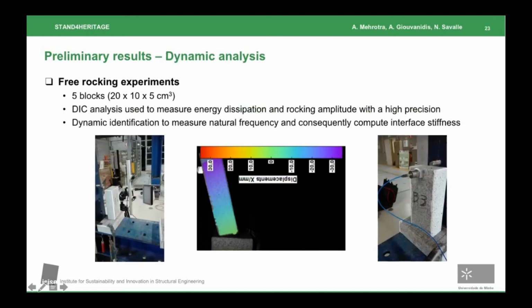In terms of dynamic analyses, free rocking experiments were recently carried out in the lab using 5 blocks with dimensions of 20 by 10 by 5 centimeters. 20 tests, or 10 for each side, were conducted for each of the 5 rocking blocks. DIC analysis was then used to measure the energy dissipation and rocking amplitude with a high level of precision, while dynamic identification was used to measure the natural frequency and consequently to compute the interface stiffness.